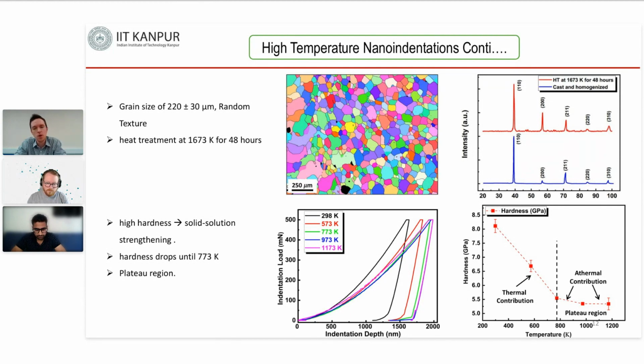That's not always possible, but generally speaking, flat and as smooth as possible, especially for testing at very high temperatures. At room temperature, you don't have as many restrictions in terms of number of indents, just perform a large number of indents. But as we said, tip wear is more of an issue at very high temperatures, so you want to try and limit the number of indents you do. You can't really do hundreds of indents at very high temperatures where you might do that at room temperature. Therefore, for testing at these very high temperatures, you do need to pay particular attention to surface preparation to get it as good as you can.